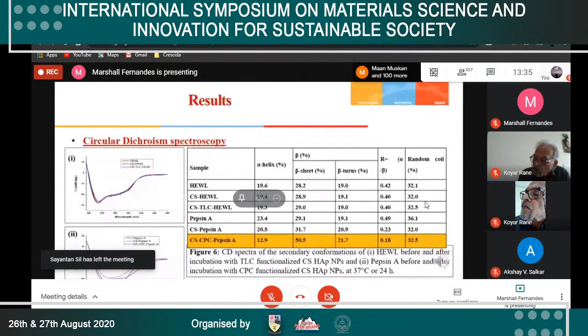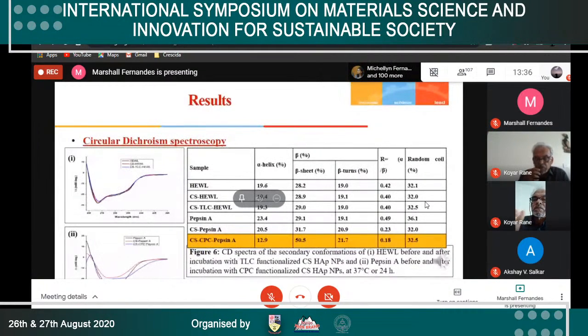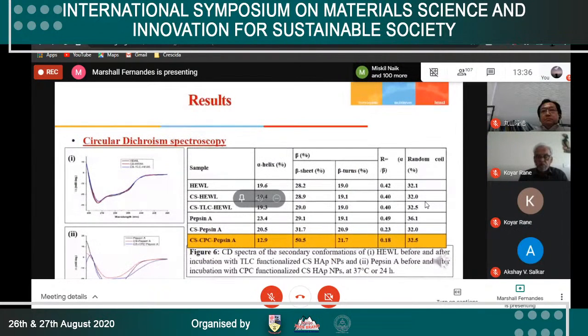TLC and CPC have lithium and chloride counter ions available for diffusion into the bound proteins and are expected to induce conformational changes. However, in the present study, such changes were noted only for pepsin A and not for HEWL. This could possibly be attributed to the fact that lithium gets immobilized on the negative surface charges of the nanoparticles and is not available for diffusion. The negative charges on the nanoparticles assist the diffusion of chloride ions into the protein, leading to the unfolding of pepsin A.